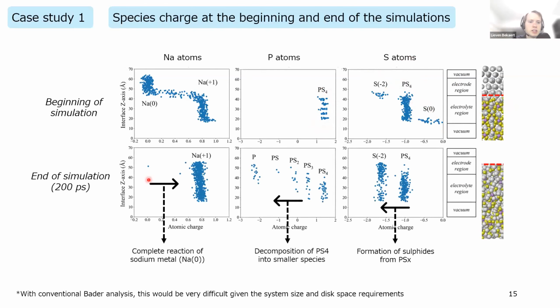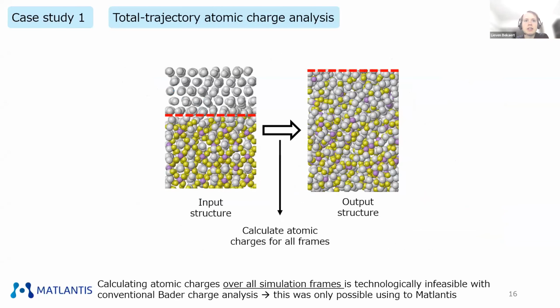And what happens at the end of the simulation is you can see that most of the sodium has reacted. All of the sodium metal has produced sodium +1, so sodium ions. We also very nicely see how these PS4 groups have decomposed into PS3, PS2, PS, and eventually phosphide groups. And you can also see how many of each are available. So it also shows which, for example, groups are more unstable than others. And the sulfides have also formed, and you can also see exactly where those sulfides have formed. So once again, with Matlantis, you're able to get this data in less than a second for all of the atoms in just one simulation frame. So this is a very significant improvement over conventional ab initio techniques.